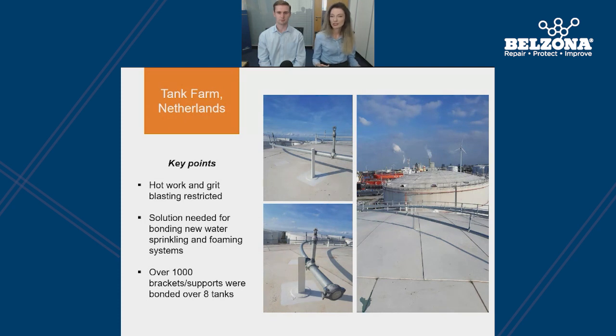We chose these case studies to show you that cold bonding can be used for plates and so much more. In this case study, the company wanted to bond a water sprinkling system and a foaming system on top of their oil tanks. However, once again, hot work and grit blasting were banned on site, obviously. Therefore, for each tank, the substrate was prepared, this time with a dust-free blasting system, in order to achieve the right surface roughness, without generating dust and any potential fire hazards near the oil. In total, over 1,000 brackets and supports were bonded onto the sides and tops of 8 different storage tanks, again leaving another satisfied customer.